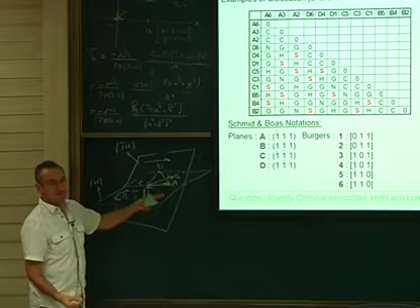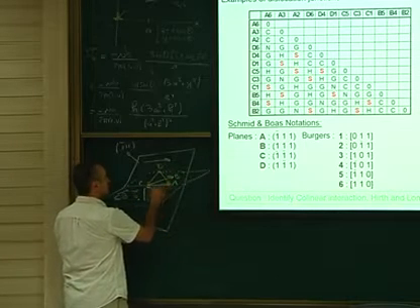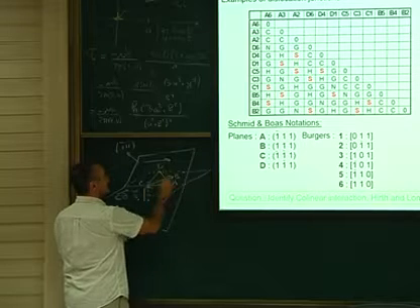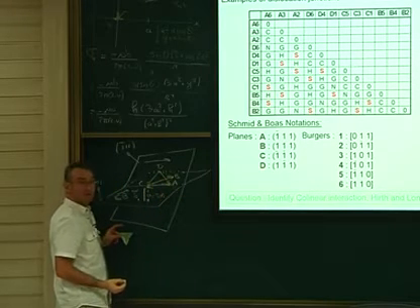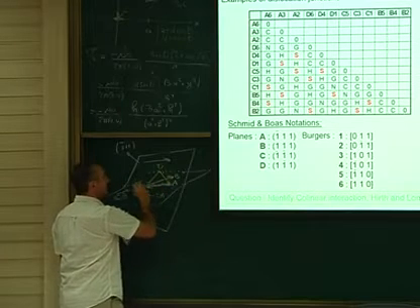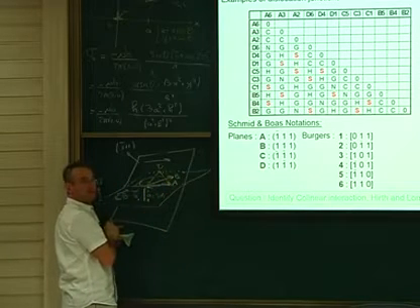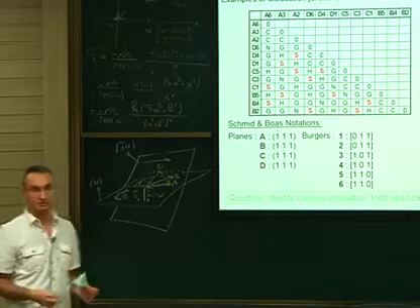If they have this line, there is no creation of a junction, but if you reverse it, AC plus CB will give AB. So AB, where is it located? In the horizontal plane. So it means that the junction you will create will be able to move in the horizontal plane. So it's not a lock. This junction can move. It's what we call a glissile junction now.